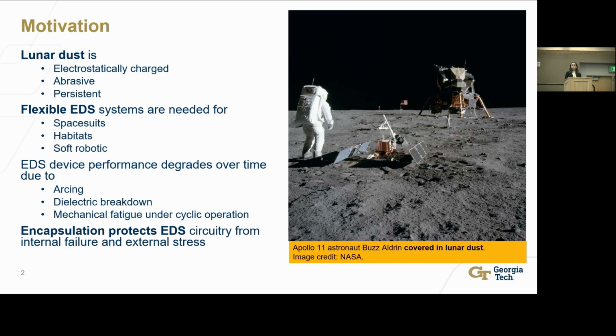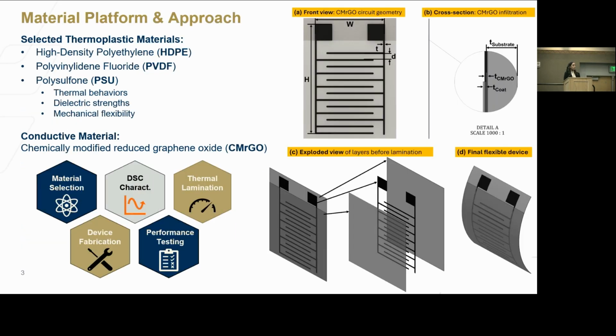However, as my colleague Luca has already pointed out, there has been some performance degradation over time for the flexible systems due to problems such as dielectric breakdowns or arcing that are utilizing CMRGO as their conductive material. Now, CMRGO is a nanoparticle of reduced graphene oxide that we have modified by introducing some dodecyl functional groups so that it can better stick to the thermoplastic substrates that I've been using to fabricate these flexible devices. And to address the dielectric breakdown issue, we decided to encapsulate our devices using a dielectric cap layer.